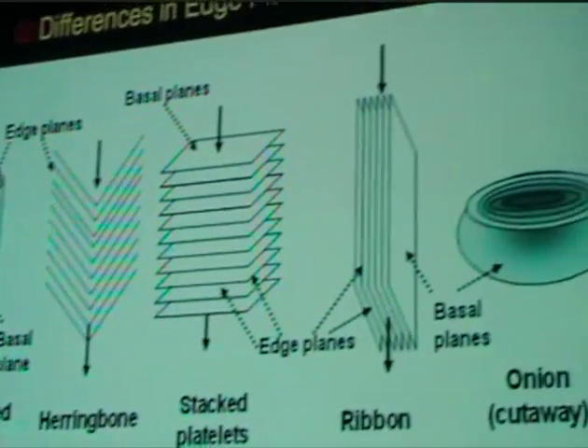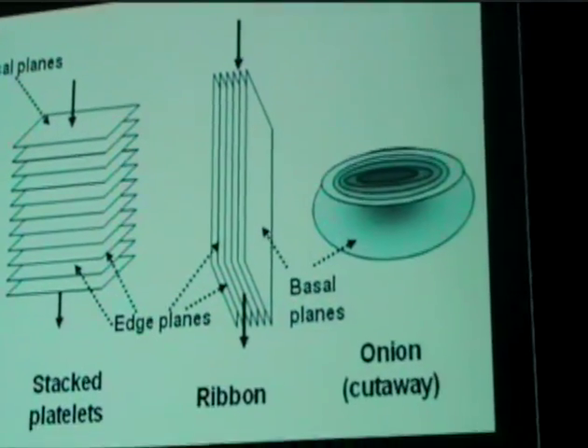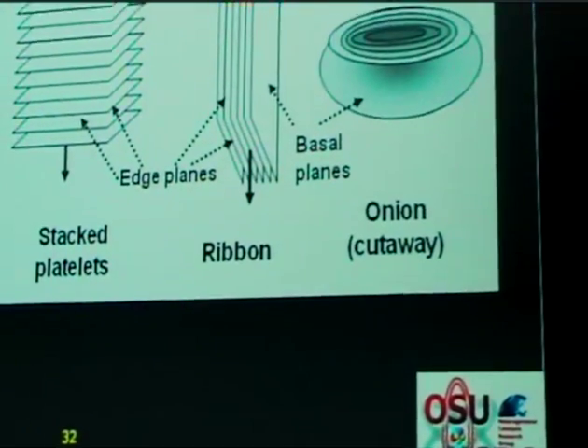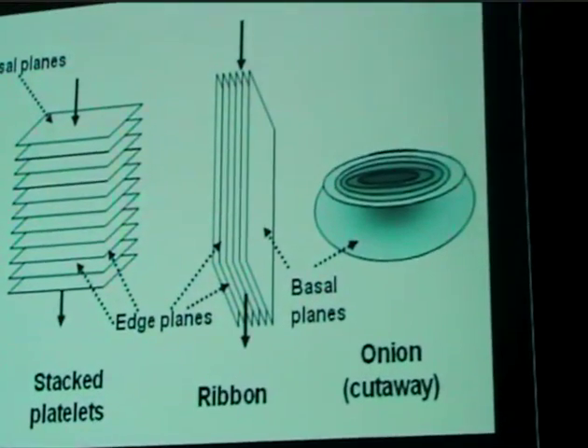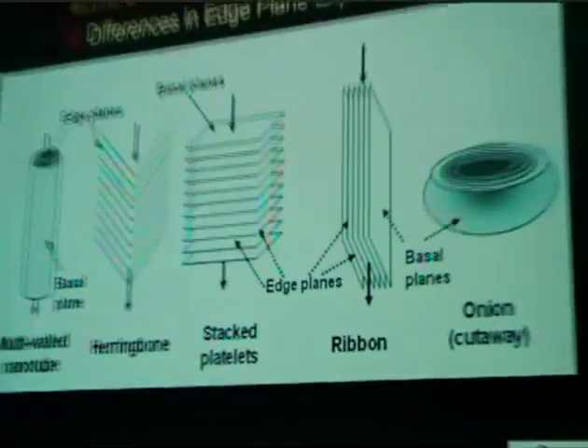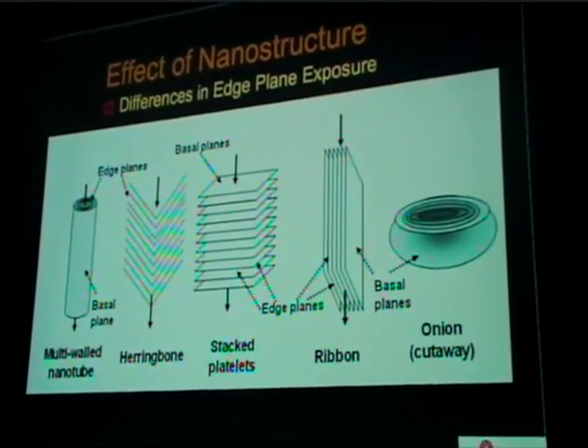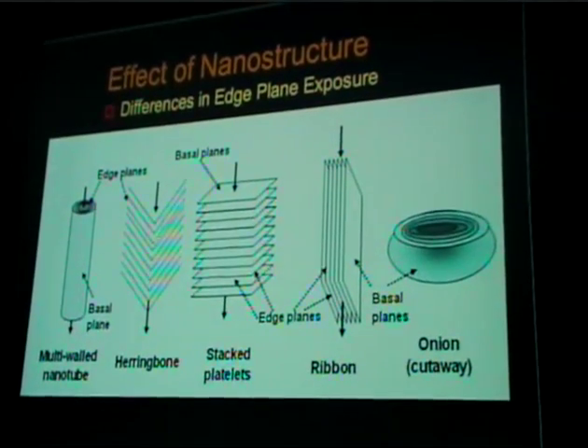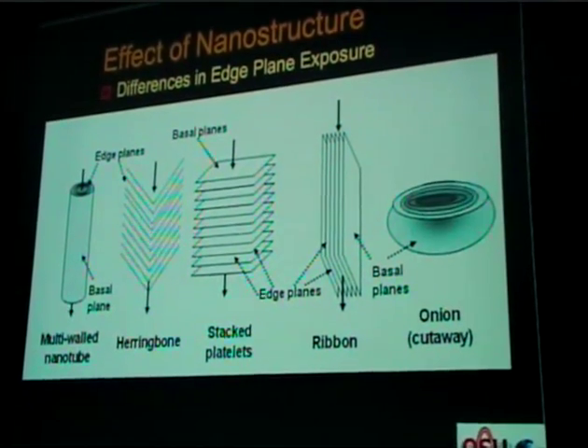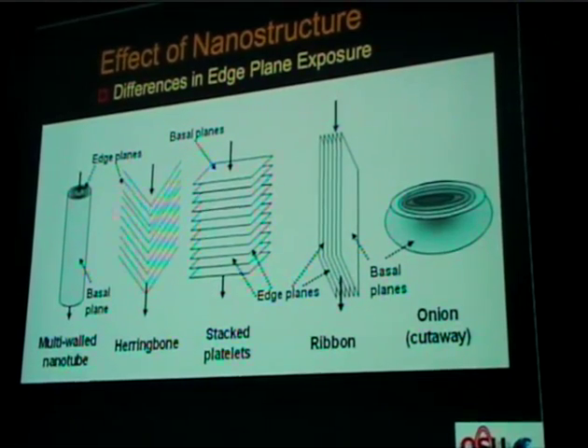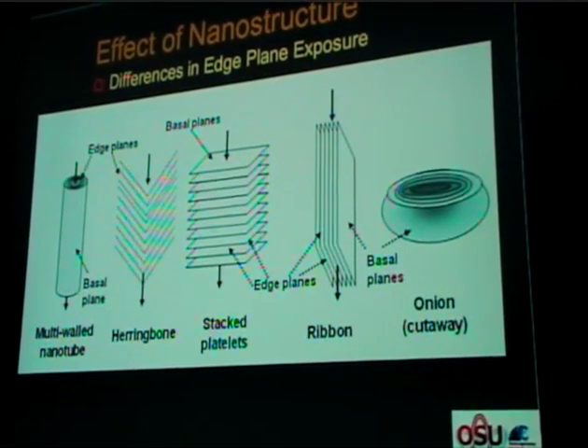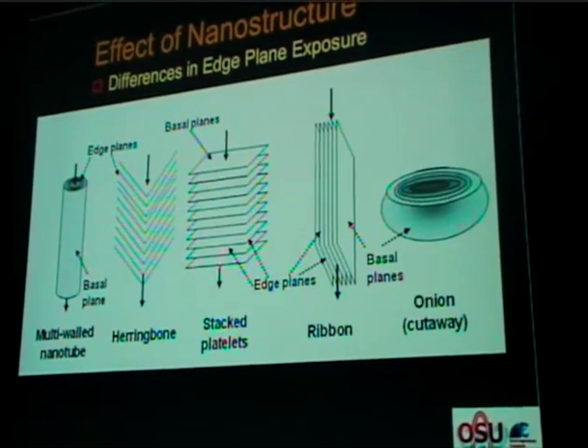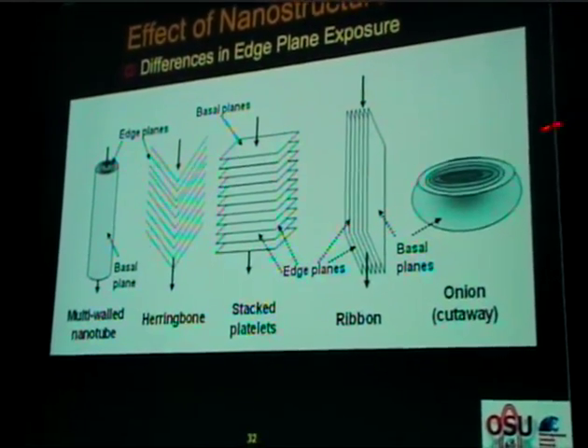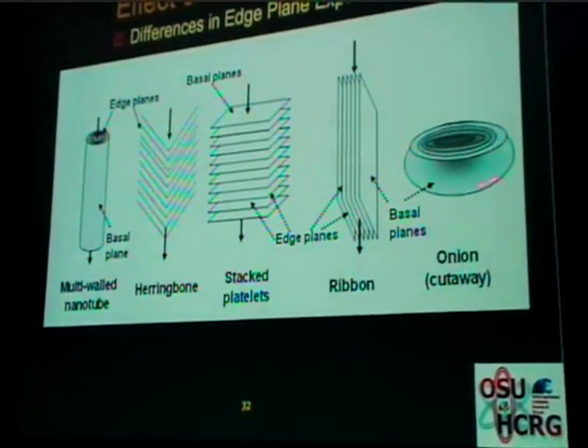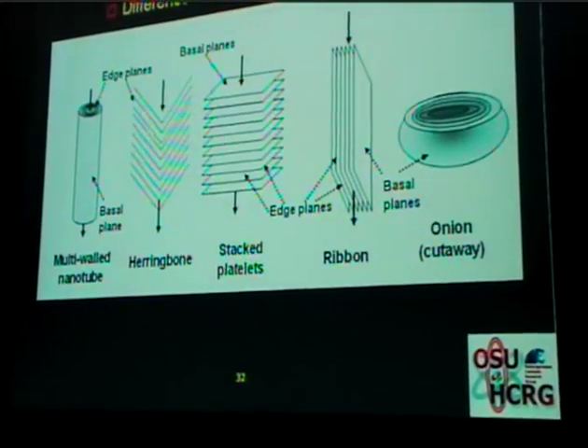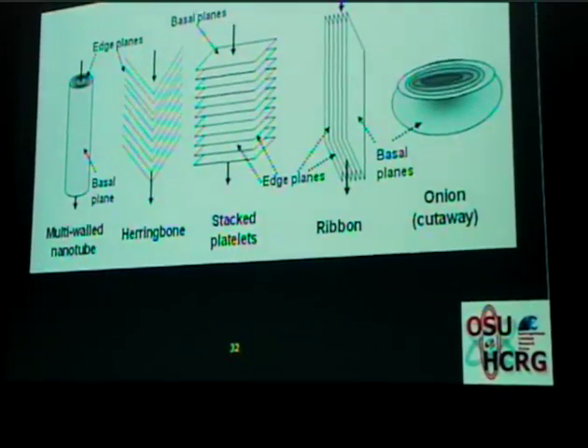And again, if we look at the different carbon nanostructures that we form, we also see that there are differences in the way the edge plane is exposed. For example, you can have the multi-walled nanotubes, and you primarily only have basal plane exposure because it's almost like sheets of paper wrapped around. If we look at structures like the herringbone, as you can see, we have much more of the edge plane being exposed. Or stacked platelets is another example, or ribbons. We also see sometimes these nano onions, and again, there is only basal plane exposure in these materials.